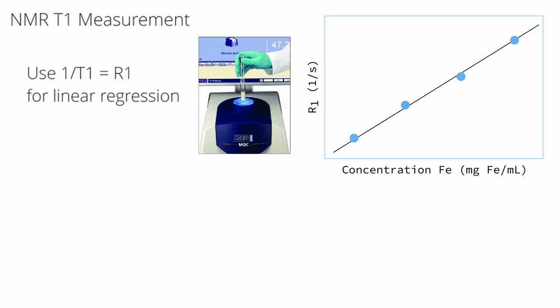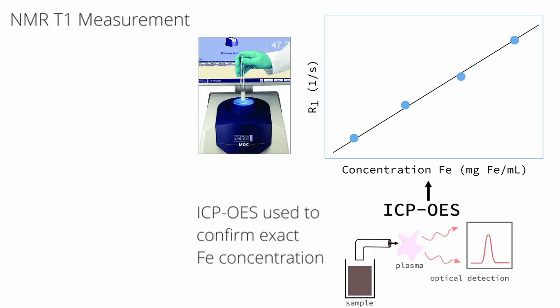To actually quantify the nanoparticle concentration from an R1, the iron concentration, which is proportional to the nanoparticle concentration, needs to be confirmed with another method, such as inductively coupled plasma optical emission spectroscopy, or ICP-OES. ICP-OES can quantify the iron content in a sample directly, and is a gold standard for iron quantification. However, it is also destructive. Using the iron content gained from ICP-OES, a given R1 can be mapped to a concentration of iron, typically in milligrams iron per milliliter sample. This must be repeated for a set of varying concentrations to establish a linear range for nanoparticle detection.